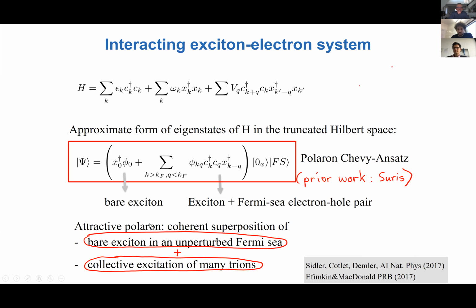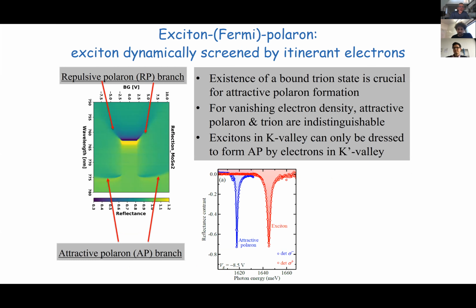And basically, it is the bare exciton part, or the quasi-particle weight, that is responsible for the strong oscillator strength of the attractive polaron. So what I would like to emphasize here is that the attractive polaron lines can be extremely narrow, even narrower than the exciton. So that is really a very nice demonstration that even though we have electrons in the system, the main effect is the renormalization of the energies or creation of new resonances rather than line broadening due to incoherent scattering.